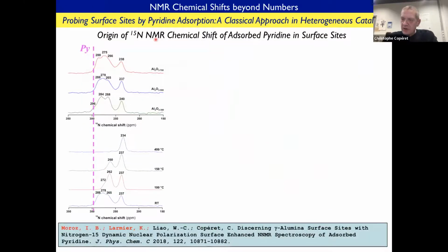A typical example that we teach in surface chemistry is that in the field of heterogeneous catalysis, a lot of people use probe molecules like pyridine to try to understand the acidity of surfaces. When you add adsorbed pyridine on the surface, you see a very complex spectrum, and all these lines correspond to specific pyridine interacting with the surface of an oxide material. While free pyridine is expected at this chemical shift, there is actually a strong shielding of this pyridine upon adsorption of a molecule. What we know is that this one corresponds to a pyridine that has abstracted a proton at the surface, so it's a pyridinium, while all these other peaks correspond to pyridine interacting strongly with surface sites.